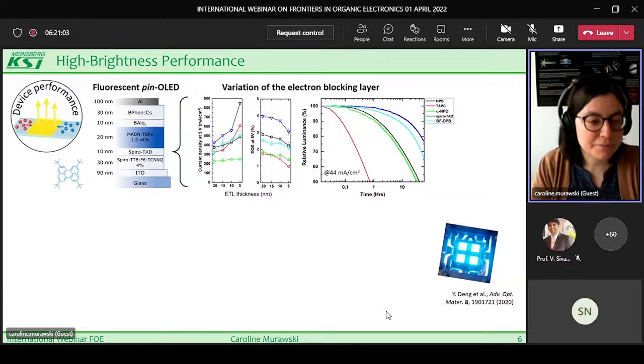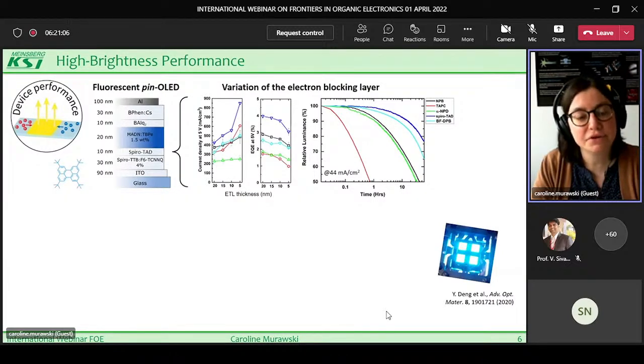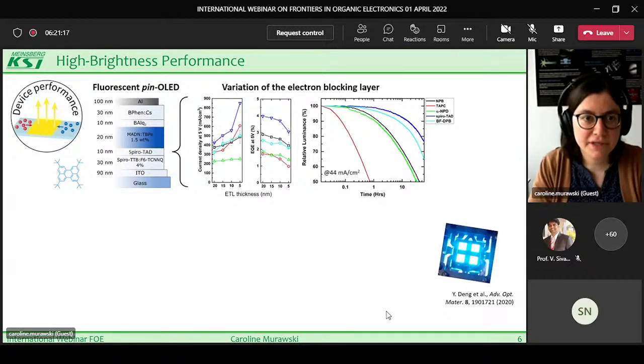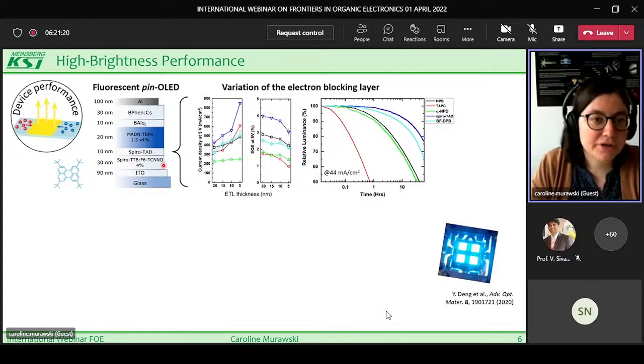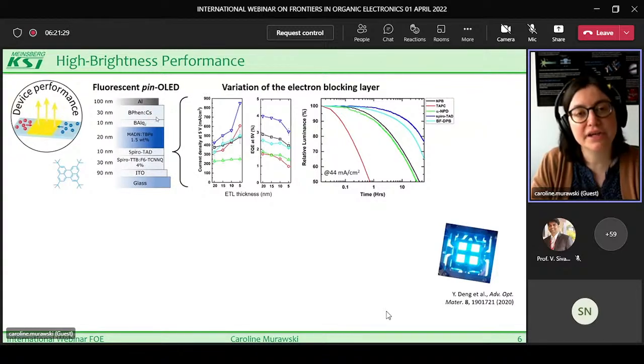This is required, for example, if we want to incorporate OLEDs later on silicon CMOS driver electronics, which are often limited to 5 volts. So we want as high a luminance at 5 volts as possible. For this reason, we also use doped charge transport layers. We have a p-dopant, F6-TCNNQ, and an n-dopant, cesium, in order to have very good charge injection from the electrodes, and also no voltage drop across these two transport layers, but instead the voltage drop only over the intrinsic layers.